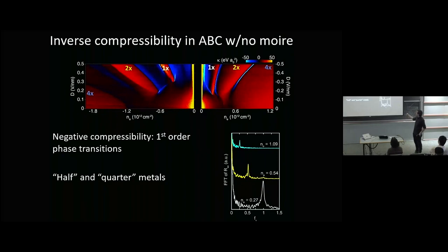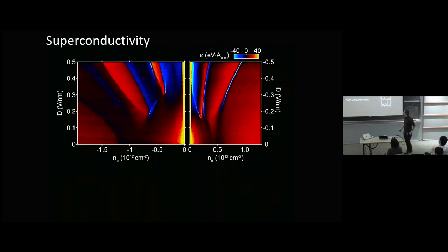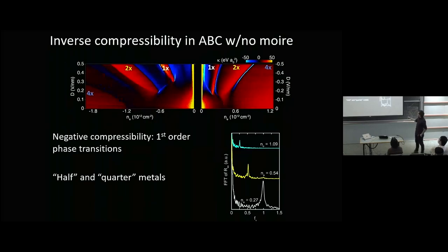So I go from a symmetric metal, spin and valley symmetric metal, to what turns out to be a spin polarized half metal. So it's all one spin flavor, and both valleys are equally occupied. And then finally, a spin and valley polarized quarter metal. Okay? And you can tell that this is spin polarized and this one is also valley polarized from things like anomalous Hall or in-plane field dependence of these phase transitions. That's all something that you can work out pretty directly, especially for electrons here, which are quite simple.